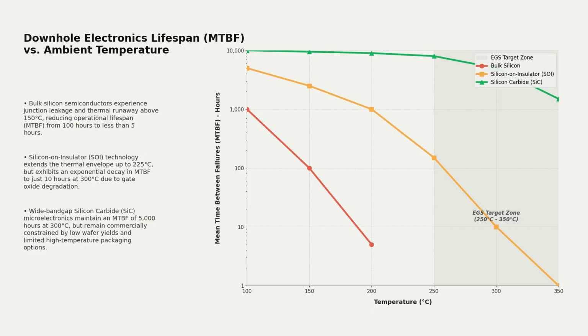Silicon-on-insulator technology extends this limit to 225 degrees, but decays exponentially at 300 degrees. Wide bandgap silicon carbide microelectronics maintain 5,000 hours of operation at 300 degrees, but face severe supply chain constraints and low wafer yields. This material bottleneck restricts real-time telemetry and directional drilling in deep geothermal reservoirs.